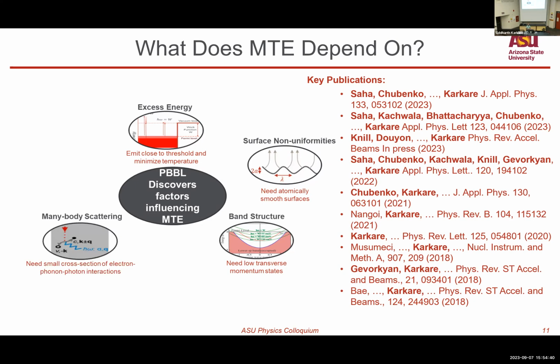Then we have many body scattering. Sometimes the scattering cross-section of many body processes like electron-phonon and electron-photon processes are quite large, especially in polarized materials. In which case electrons can absorb a phonon during excitation and get excited into large transverse momentum states, giving large mean transverse energy. And then there's nonlinear photoemission. Electrons can actually absorb 2 photons, even if they are close to the work function, they can absorb 2 photons and get excited to a very high excess energy. And that creates lots of problems, increasing mean transverse energy.